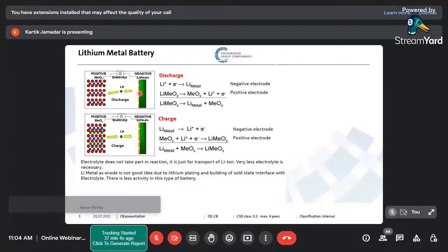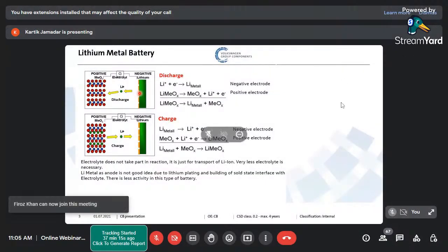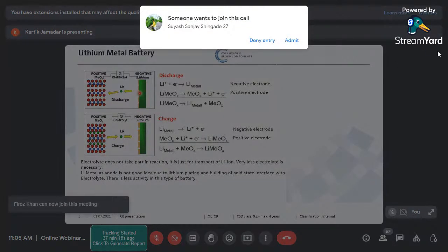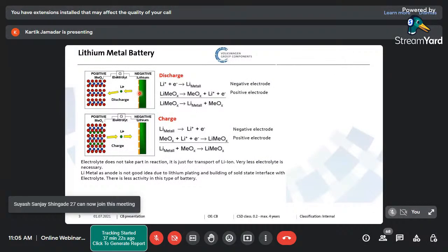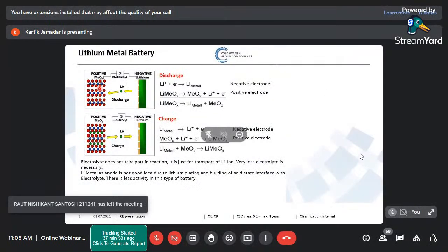And what is the advantage of it? That you have very, very high efficiency in lithium ion technology. We are talking about 97 to 98% efficiency of this material. So you can imagine that I'm giving 100% energy, I'm getting 98%. Nothing is more efficient than that, and that can continue to around 4000 to 5000 cycles. Your capacity loss is very, very low. So it is a wonderful battery. Plus we know that lithium has a very high voltage, and the copper, this metal oxide, has around a voltage of 1.23. So we are at least getting more than 4 volts. So between 4 to 5, normally we say around 4.2 to 4.3 volt. This is at least 4 times more than the conventional voltage which we know with the lead acid battery.